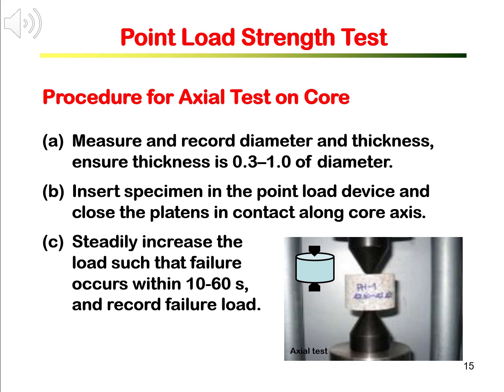After measuring and recording the specimen thickness and diameter, we insert the specimen in the point load device and close the platen to contact the core end in the center. The loading point is on the center of the circular plane, as shown by the illustration on the right.